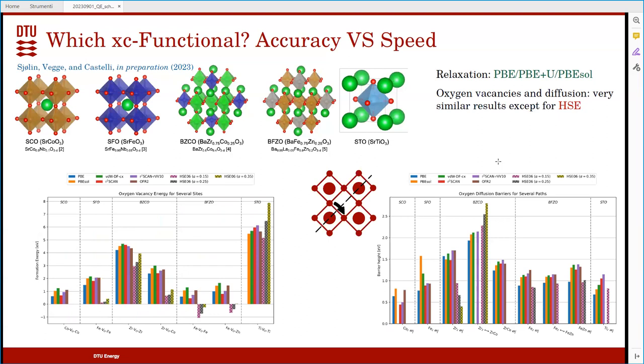So we are looking at one oxygen going from one place to the next. And we've been talking the last few days about how to use the plus U when you do NEB calculations, and you should be very careful, because in most of the cases, NEB is fine. But if you have an electronic occupation that changes drastically during the hopping, then you might need to use a different U. So that was when I was referring that we should try the plus U plus V, or different methods, because you might not use a consistent U through the entire path. Again, in most cases it's fine, but you need to make sure that you don't change the occupation.